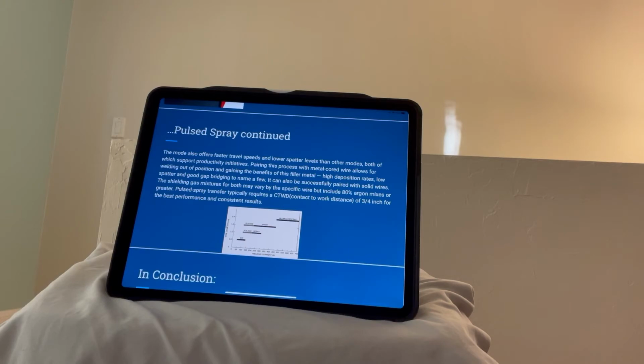It can be successfully paired with solid wires. The shielding gas mixtures for both may vary by the specific wire, but include 80% argon mixes. It typically requires a contact tip to work distance of 3/4 of an inch for the best performance and consistent results.